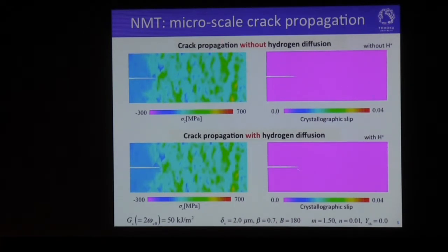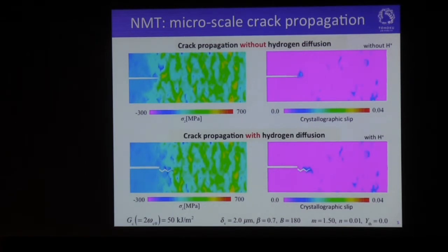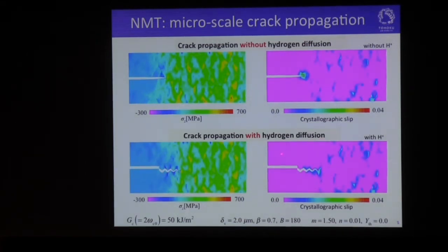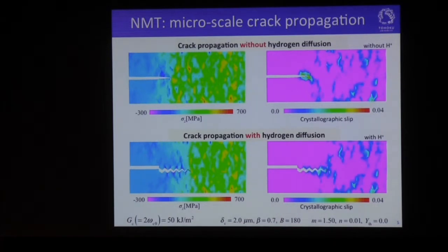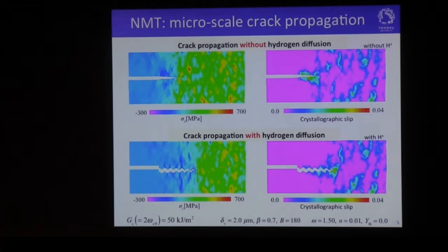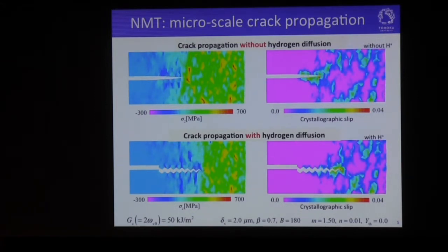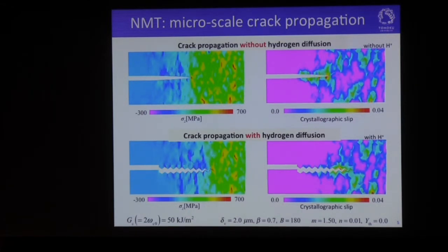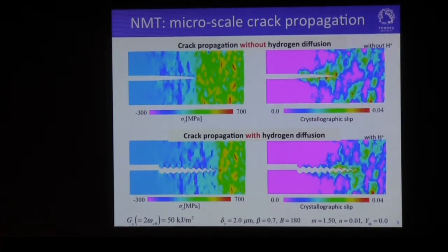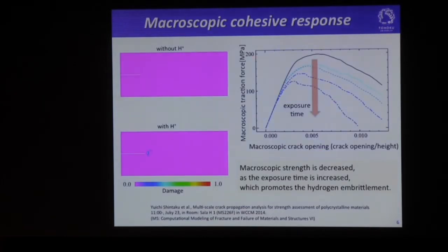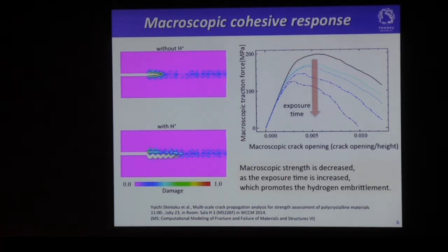This upper one shows the crack propagation without hydrogen diffusion. On the other hand, here is the result with hydrogen diffusion. As you can see, the crack speed is much higher than in this result, because this material is subject to hydrogen diffusion and suffers from hydrogen embrittlement at the microscale. This result is also reflected in the macroscopic cohesive response. Here shows the relationship between the macroscopic crack opening and the macroscopic traction force. As you can see, the macroscopic strength is decreased as the exposure time to the hydrogen is increased, which promotes the hydrogen embrittlement.